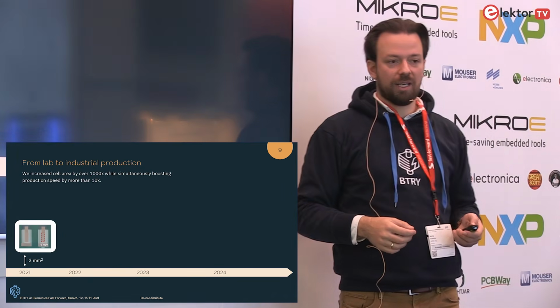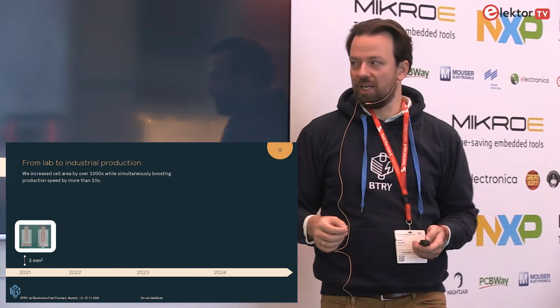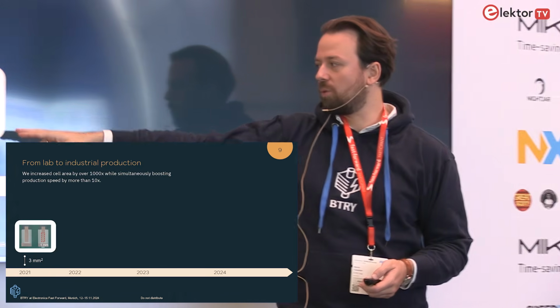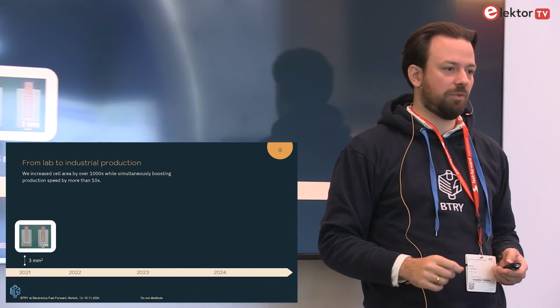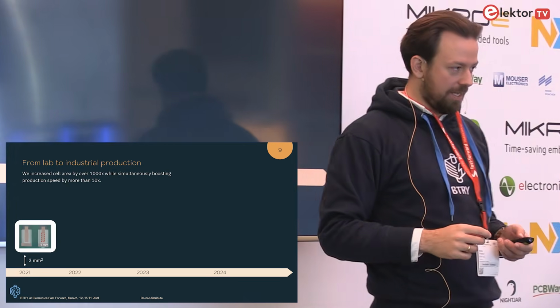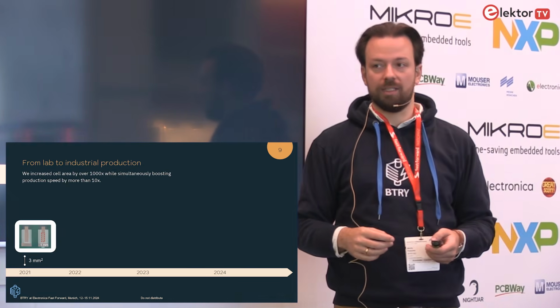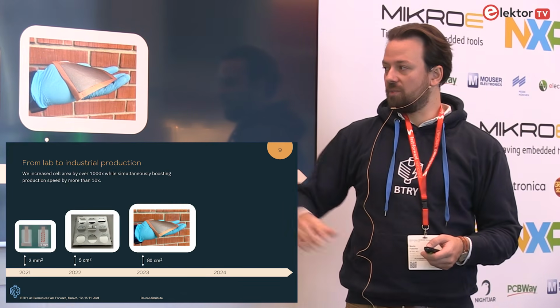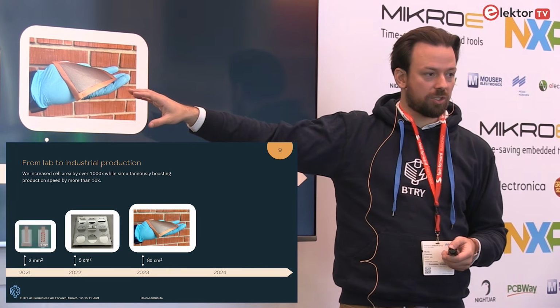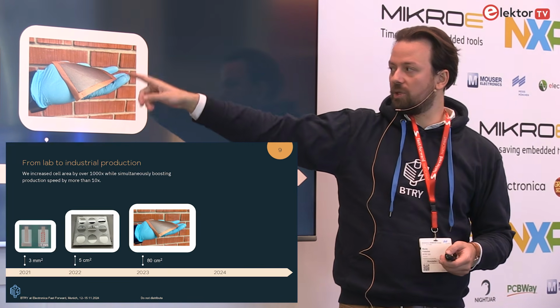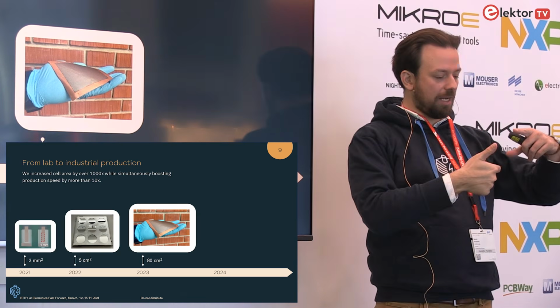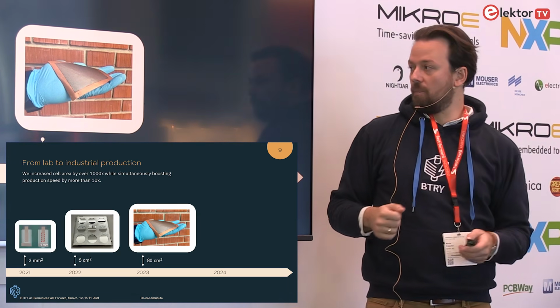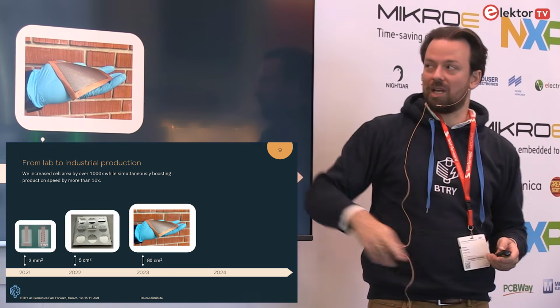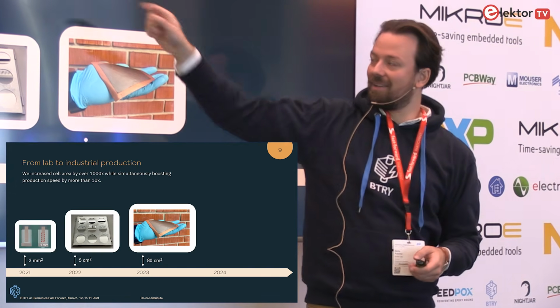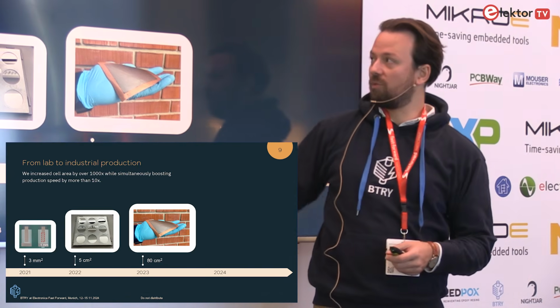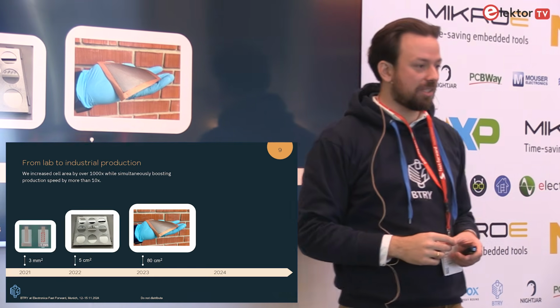Now, this has all been done in the research group, meaning that we had very small areas. This is typically what we worked with, just a few square millimeters in size. Since then, we have spent a lot of effort on scaling this technology. This has all been done still on the research laboratory scale. At the research laboratory scale, we were able to scale this to about 10 by 10 centimeters, which is the biggest we can do in the research lab. But this is already 1,000 times greater area than what we had before.